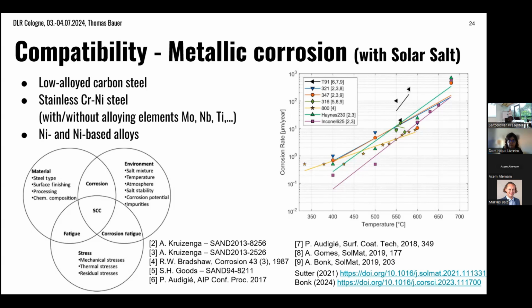And then the material itself, the steel, of course, has also different types, qualities, chemical composition, finishing, treatments, and so on. There's also a big choice on the steel side. And then you can have, in addition, also stresses. That's typically not done in the lab, but in practical application, you also have stresses in the system. And then you can have things like stress corrosion cracking, for example, if you have additional phenomena. There has been very limited work in the laboratory to address this, but it's observed maybe rather in practical systems if you have an issue with this additional stress.